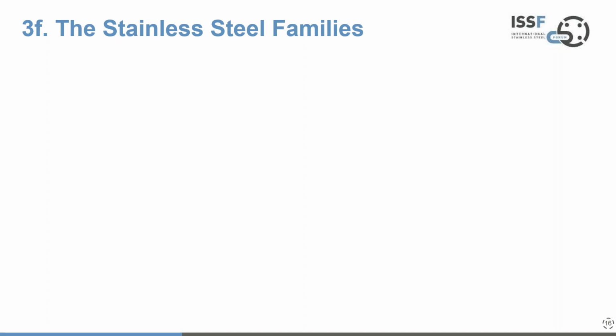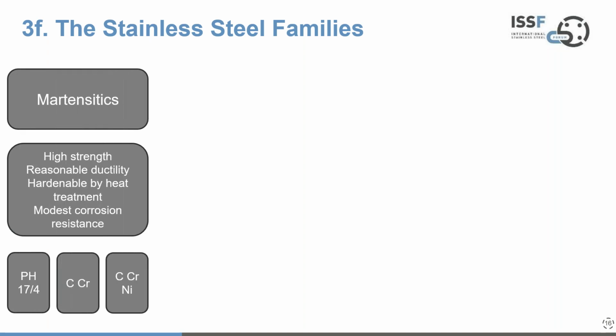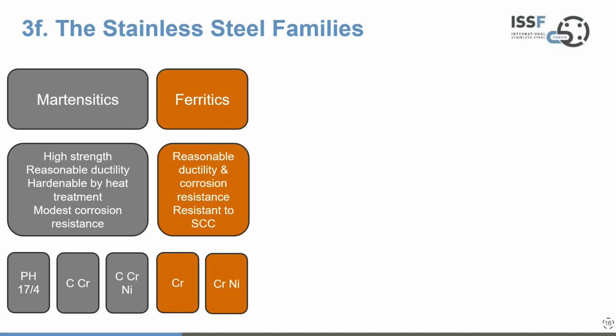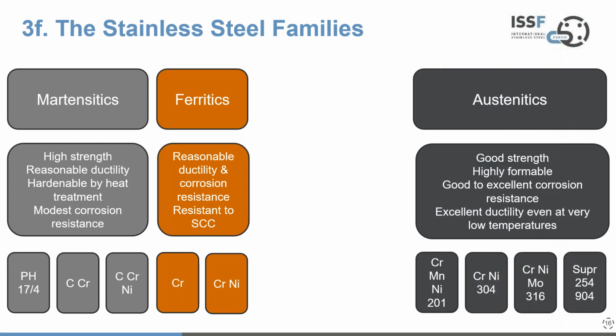Now, how do these families look together? Well, you have the martensitic group, which are basically the carbon chromium or sometimes carbon chromium nickel steels, offering high strength, reasonable ductility, but more modest corrosion resistance. Then you have the ferritic group, which have reasonable ductility and corrosion resistance. These are resistant to a form of corrosion called stress corrosion, which leads to stress corrosion cracking. And then you have the austenitic group, which is much more well known. With good strength, these are highly formable, good to excellent corrosion resistance, as I said. And these products don't suffer a transition from a ductile form to a brittle form, even at very low temperatures, which is another advantage of the austenitic group.